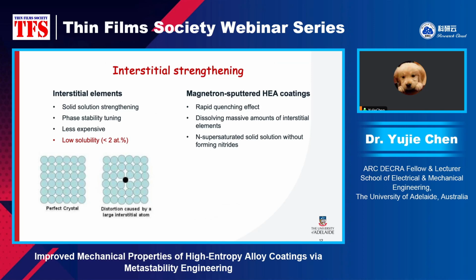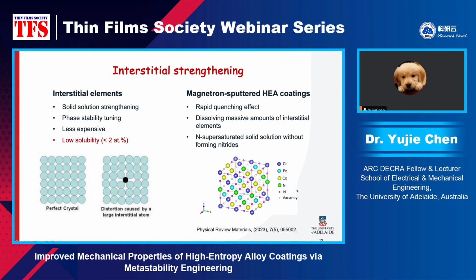And if we suppress the diffusion, we will suppress the formation of nitride, because for nitride formation, the metal elements and the nitrogen need to come together to form the nitride, right? So if we suppress the diffusion, we are going to form the random or disordered solid solution phase. That means we can dissolve a large amount of interstitial elements. Right, this rapid quenching effect promotes the formation of disordered solid solution phase. So by using magnetron sputtering, we are able to produce a solid solution phase supersaturated with nitrogen without forming any nitride.